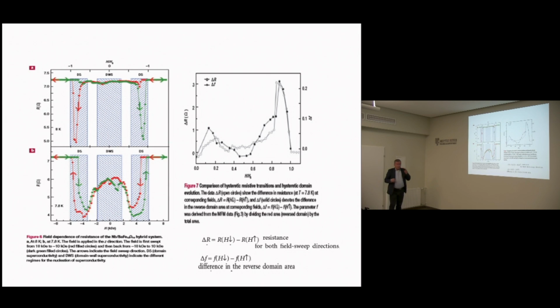Now, how to understand this behavior? First of all, here we see the dependence of resistance versus magnetic field. If we go from plus 10 kilo-oersted and then decrease the field, then we have some minimum. This is very close to Tc. And then on the opposite side, a strong dip of the resistance. And then if we lower the temperature, more or less the situation is the same. However, the dips are almost comparable.